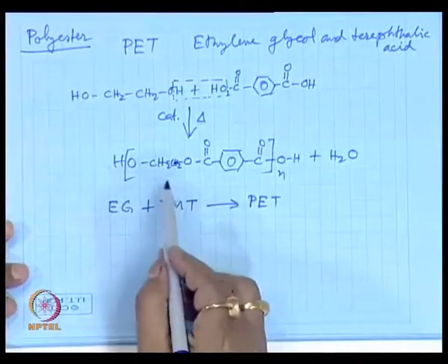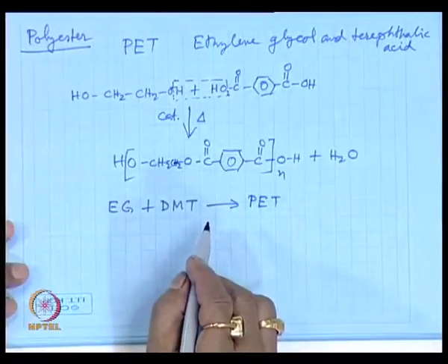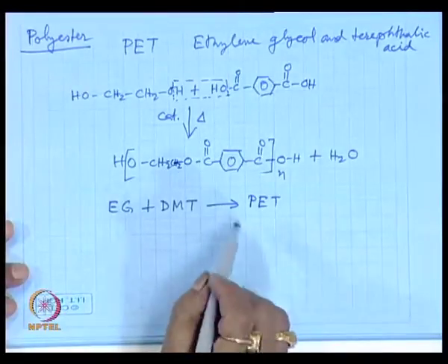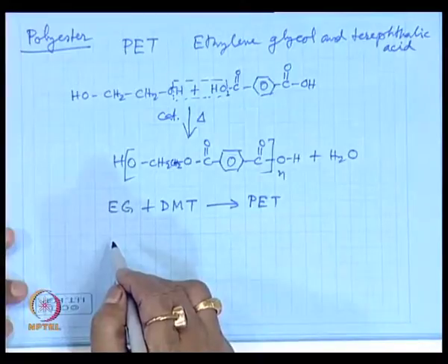This is a saturated polyester, you can have unsaturated polyester too. If you react maleic anhydride with ethylene glycol or other alcohol, you will find unsaturated polyester. Today unsaturated polyester finds a large consumption in laminating industries, in composite industries, and then polylactic acid, polylactate, polylactides, polyglycolic acids, copolymers of polylactic acid, polyglycolic acid, polylactide co-glycolide,